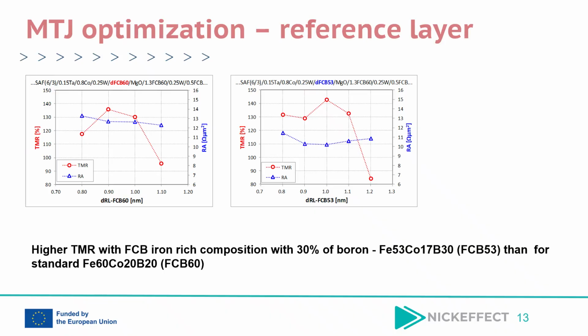The next optimization step focused on the reference layer composition and thickness in order to further improve the TMR ratio while maintaining favorable RA values. This slide compares MTJ structures based on two different FeCoB reference layer compositions: the standard 60-20-20, FCB60, and a 53-17-30, FCB53, containing 30% of boron. The graph on the left presents the dependence of TMR and RA on the thickness of the FCB60 reference layer. The highest TMR values, around 135%, were obtained for RL thicknesses close to 0.9 to 1 nanometer, while RA product remained in the range of approximately 12 to 13 ohm micrometer squared.